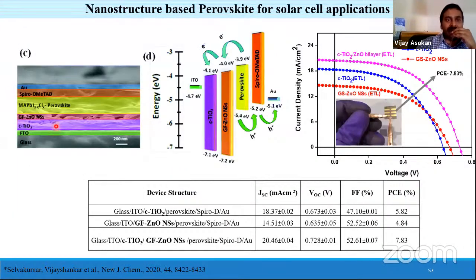So this is how we constructed it by using zinc oxide nanostructures above the compact titanium dioxide, over the interface between perovskite and titanium dioxide. Here we have used a traditional hole transport layer. Of course, we have used different hole transport layers, but at least within this paper, the report shown here is using spiro hole transport layers.